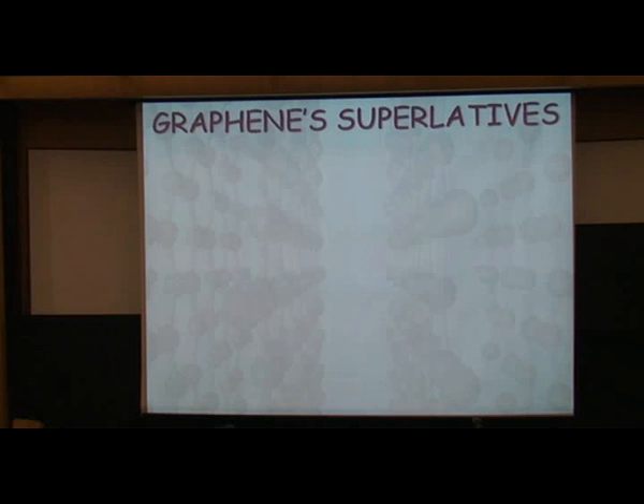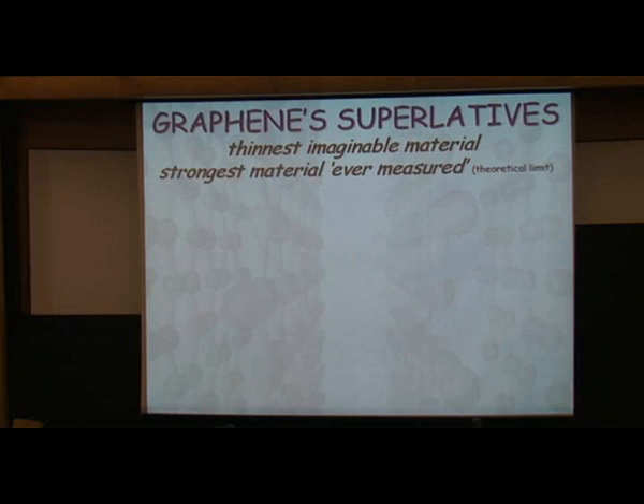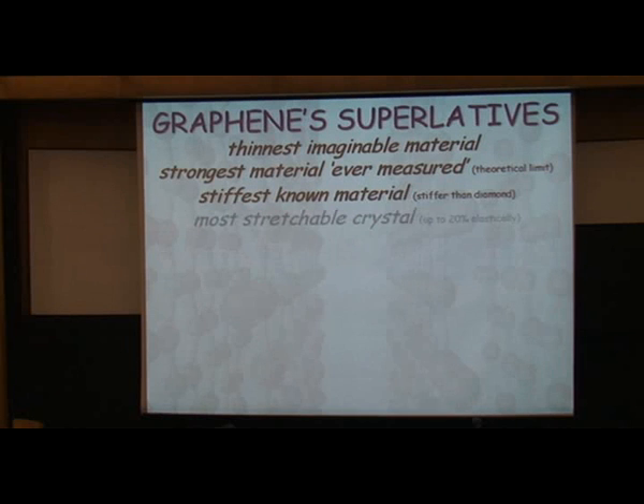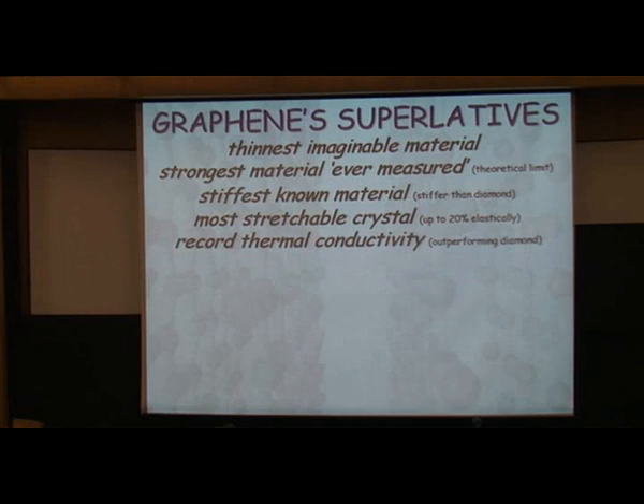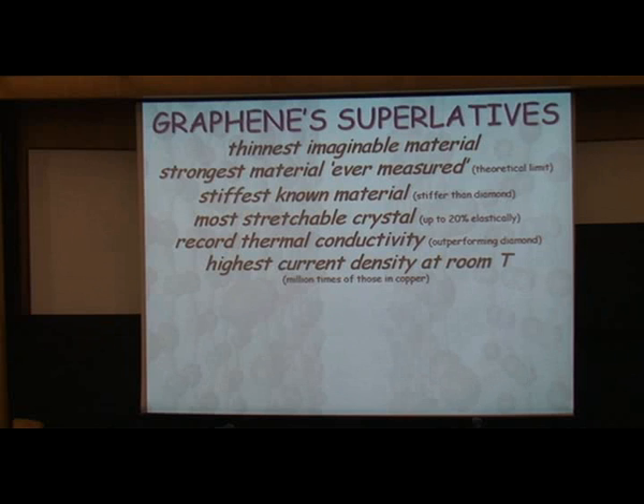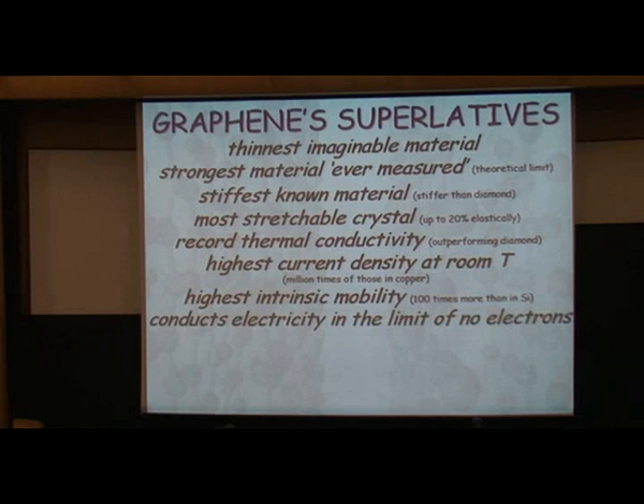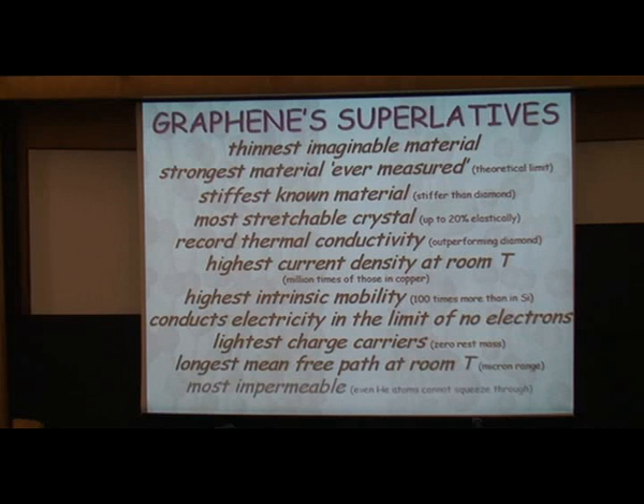So what's so special about graphene? Over the last 5 years, we learned that graphene has plenty of superlatives. Of course, you can't imagine any thinner material than 1 atom thick. It has been measured that it's a very strong material, approaching the theoretical limit. It's the stiffest material. We know it's stiffer than diamond. It's stretchable at the same time by nearly 20% elastically. It shows record thermal conductivity. It allows currents 1,000,000 times larger than copper allows at room temperature. It shows excellent electronic properties, conducts electricity in the limit of no electrons, which I will be talking about, and so on.